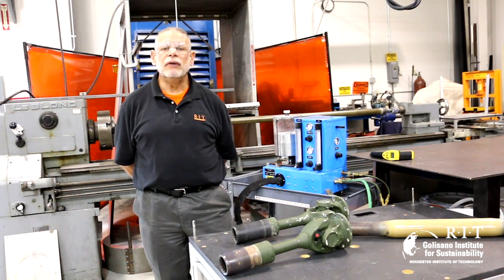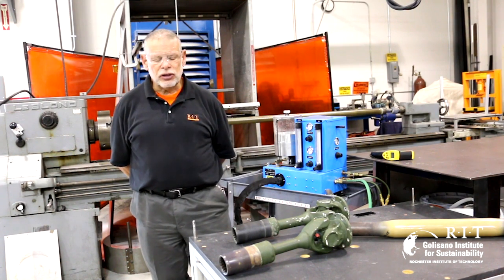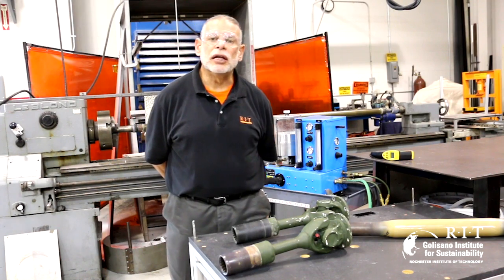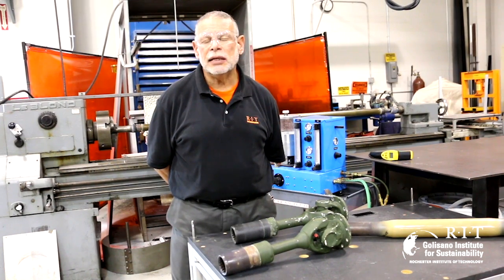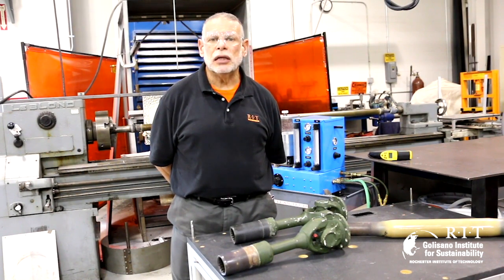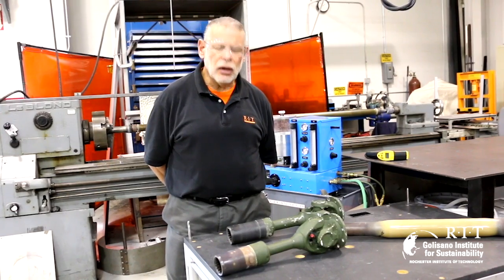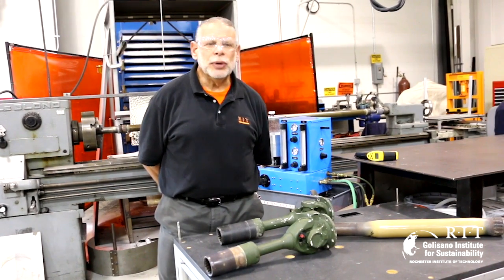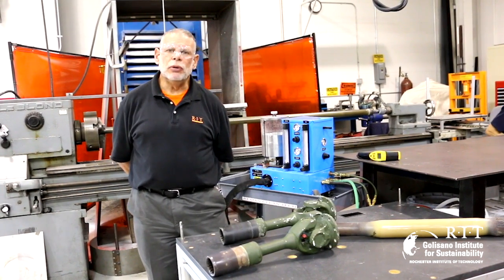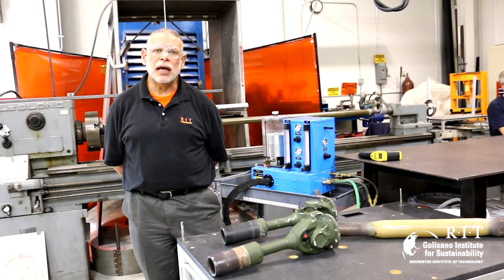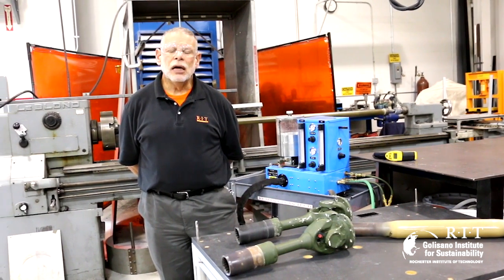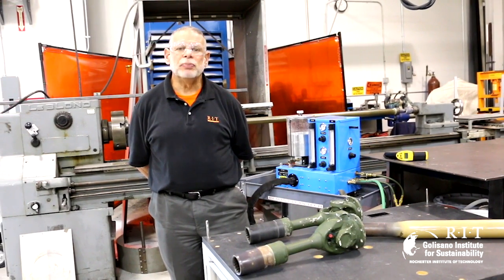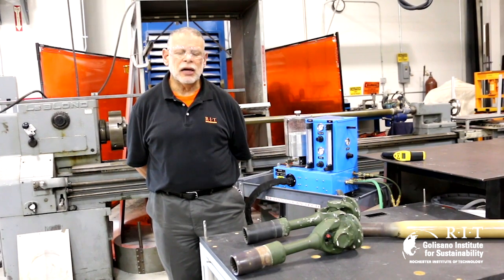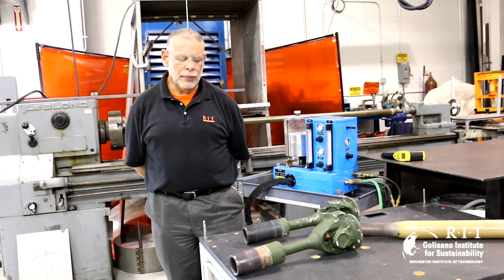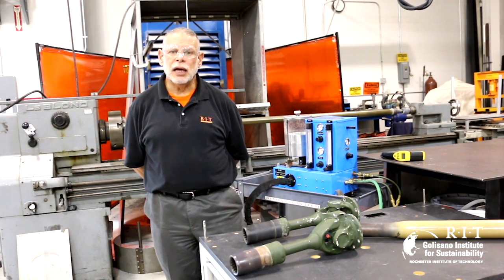However, there's a couple of constraints. First, you can't touch the inner coating and the spline. And secondly, you can't take off the U-joint on the back end. So I said, okay, that shouldn't be a problem. So we came up with a process where we would machine off the coating on the top, and then we would flame spray on plastic, a thermoplastic on the surface, to replace the coating and make it as good as new.